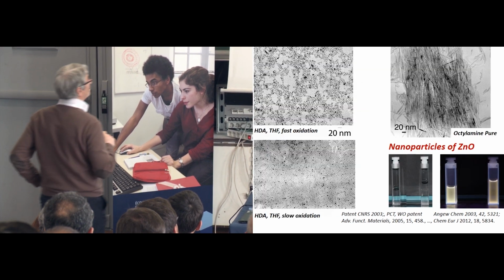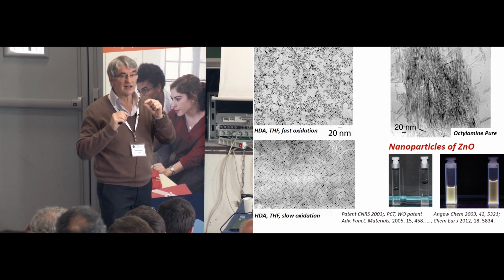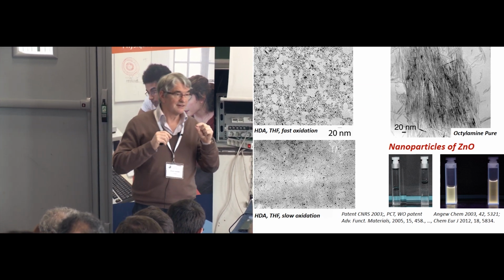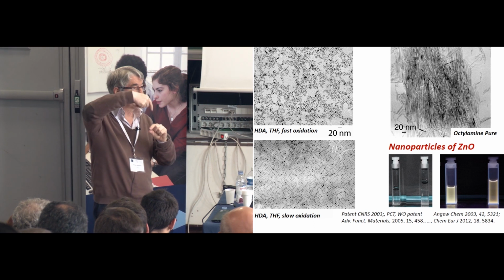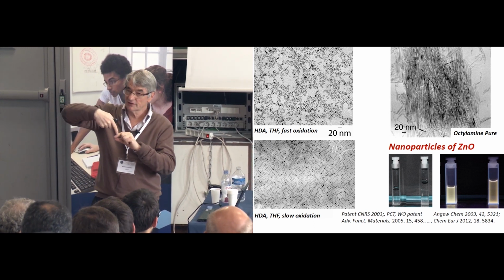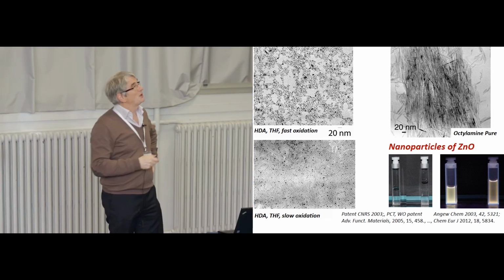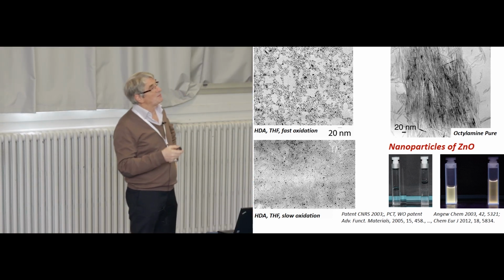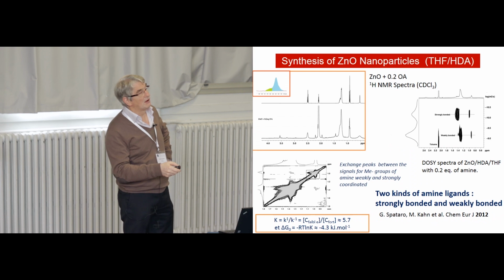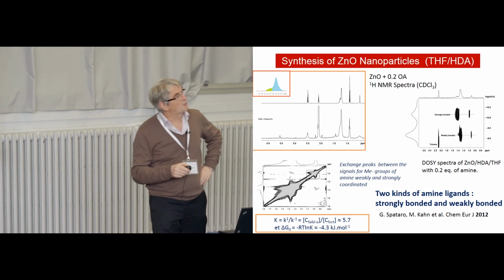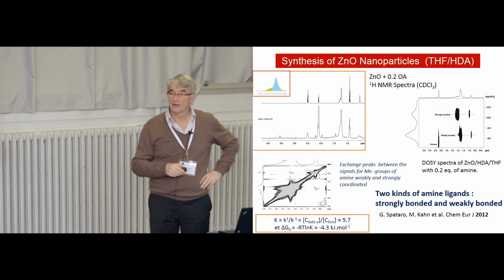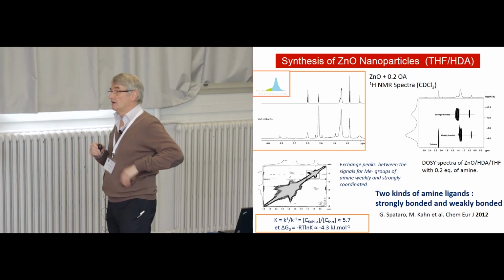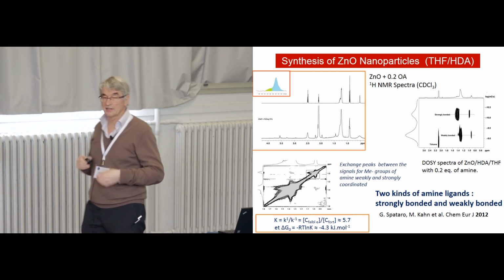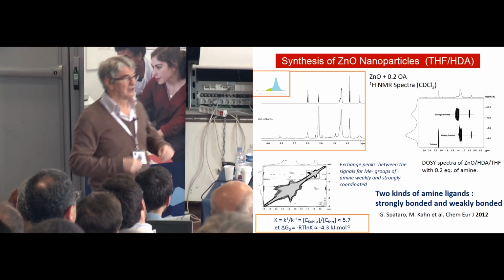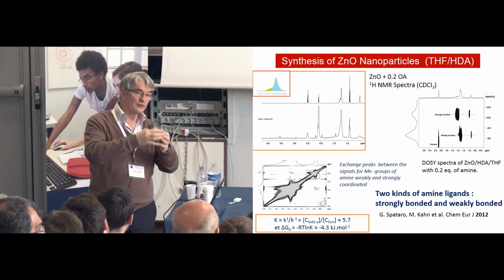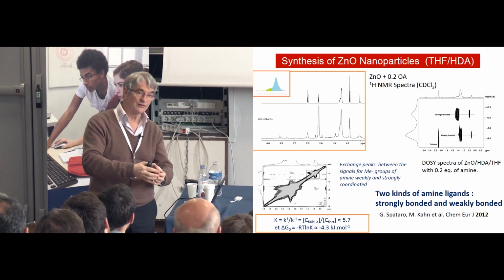The interesting thing is that zinc oxide at small size is an ideal system to study the coordination of surfactant at the surface. So we could play with acids, amines, here octylamine or hexadecylamine, and we could play with different NMR techniques. Again, I will not enter into detail, but the DOSY here allows you to measure the diffusion of the particle into the solution.